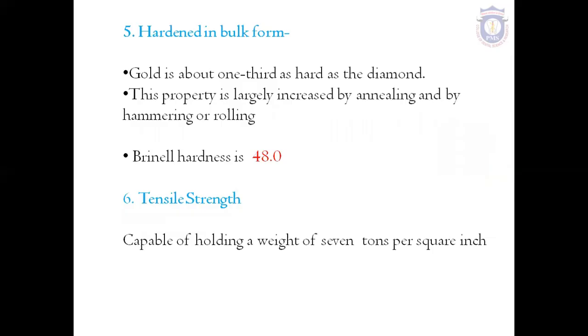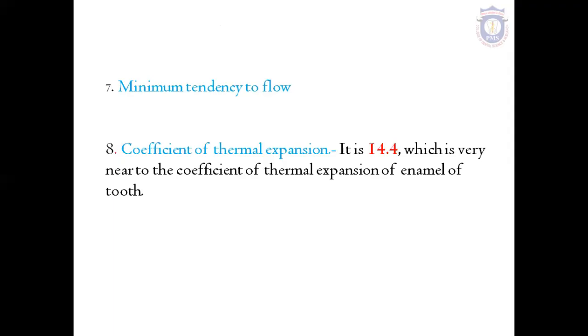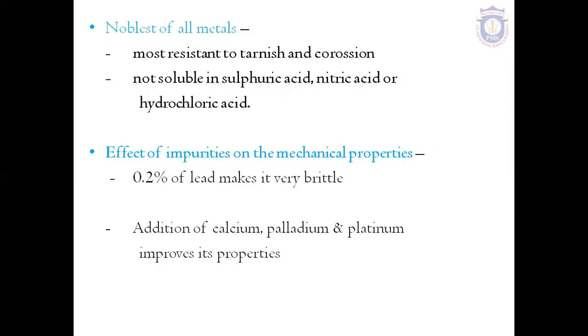Gold is about 1/3 as hard as diamond. As mentioned before, its hardness can be largely increased by hammering or rolling, which is a form of working on it, or by annealing, which is a heat treatment. The Brinell hardness number is 48. Tensile strength: it is capable of holding a weight of 7 tons per square inch. It has minimum tendency to flow in the oral cavity. The coefficient of thermal expansion is 14.4, which is very near to that of enamel and is highly desirable. It is the noblest of all metals, that is, the most resistant to tarnish and corrosion. It is not soluble in sulfuric acid, nitric acid, or hydrochloric acid.